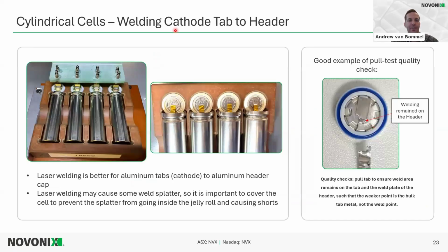For the cathode tab, laser welding is used for those aluminum tabs to the aluminum header cap. Here are 4 cells, and this is put into the laser welder, so those welds can be done. Laser welding can cause some weld splatter, so it's important to cover the cell to prevent that splatter from going inside the jelly roll, which could cause shorts.